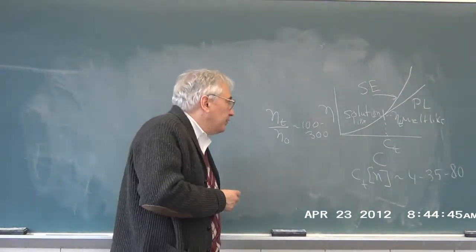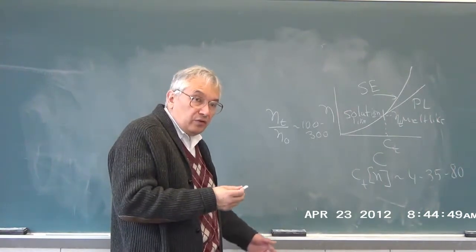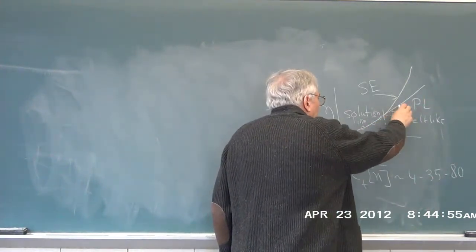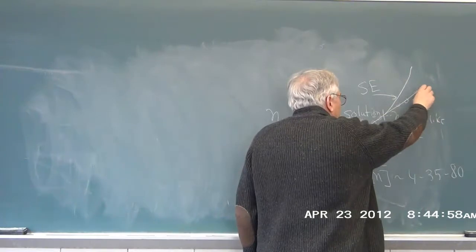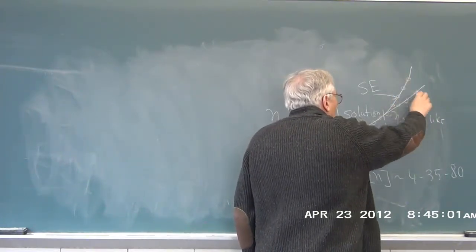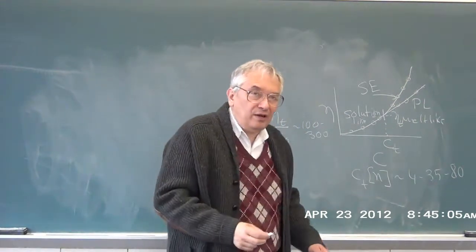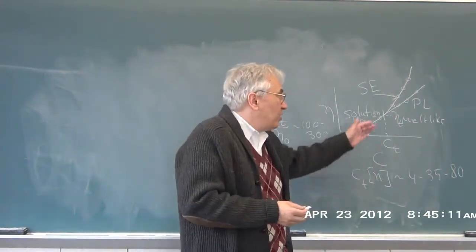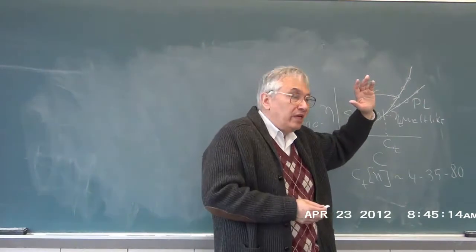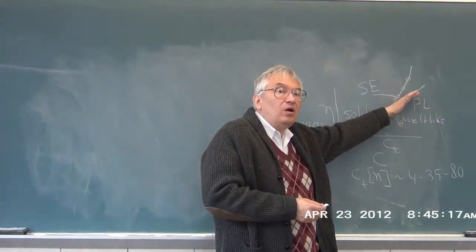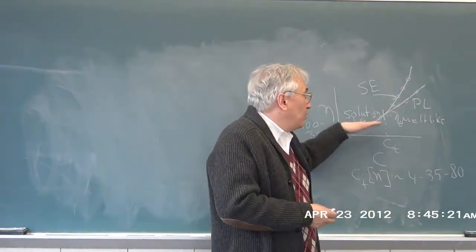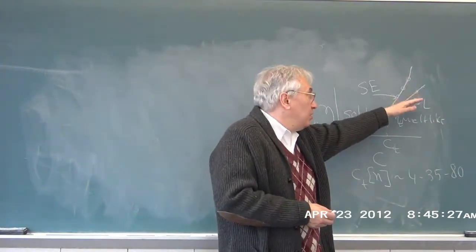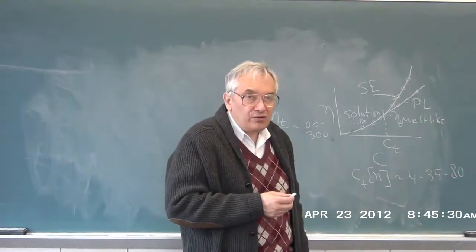Well, the answer is, if you want to interpolate, you have a number of points, and fortunately it is quite easy to tell the difference between a stretched exponential or a power law. What you do is you simply generate your log-log plot of the measurements, and it will be painfully visible whether as far out as you've gone there's nothing but stretched exponential behavior, or whether there is a crossover to power law behavior. And once you've done that, you'll know whether, if you are doing industrial type stuff, you want to use a single stretched exponential, or you need two functions and can specify a crossover.